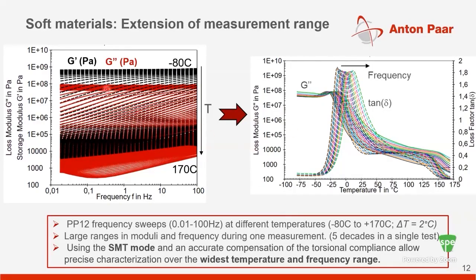Now you can also take this frequency sweep data and convert it into a temperature sweep. So you can see how this frequency sweep data can be converted into temperature sweeps at a bunch of different frequencies, and you also see the glass transition of the PSA. What I want to highlight is, if you have an SMT mode that can accurately compensate for torsional compliance, it allows for precise characterization over the widest temperature and frequency ranges in a typical rheometer experiment.